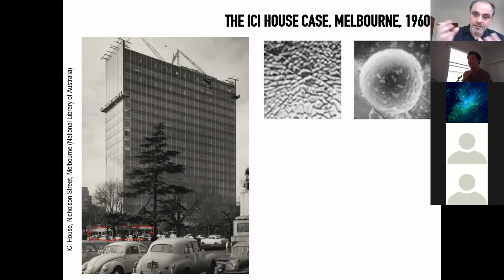But in toughened glass in particular, because the glass is put into a process of heating and cooling, these particles during the toughening process can change. First of all, they shrink, they change state, and then once the glass is put back into the environment, in time, they have a risk to revert back to their initial state and expand. Now, toughened glass is that kind of glass that if you break it, it breaks into 1,000 small pieces. And so while it is strong, once you break through its core, it explodes literally. So this phenomenon is particularly relevant and important for toughened glass.